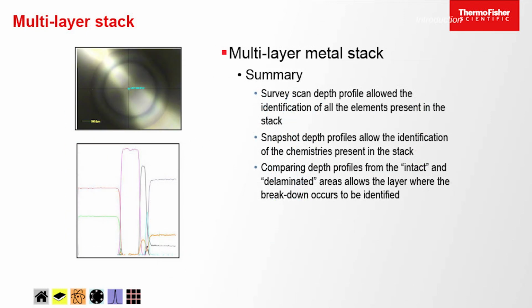And so just by doing an initial survey scan, depth profile to identify the elements that are present, then doing depth profiles to identify the chemistries that are present within the stack, and then by looking at the intact and the delaminated areas, we were able to identify exactly which position. Obviously, we had several aluminium oxide layers. We needed to know between which two layers was causing the delamination failure. And by doing the depth profiling experiment, we were able to identify very easily where that break was occurring and separate out the differences.